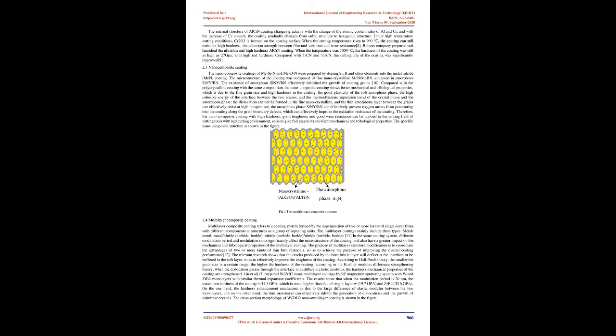Balzers company prepared and launched the ultra-thin and high hardness Al-CrN coating. When the temperature was 1000°C, the hardness of the coating was still as high as 27 GPa, with high red hardness. Compared with TiCN and TiAlN, the cutting life of the coating was significantly improved. [9]